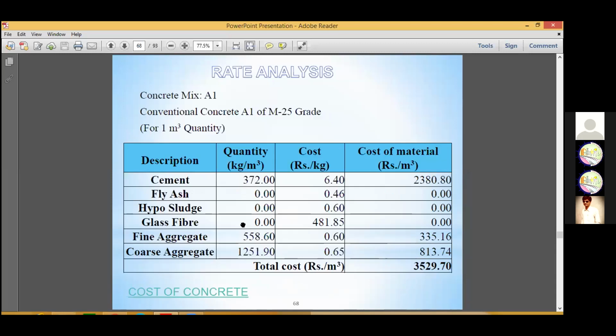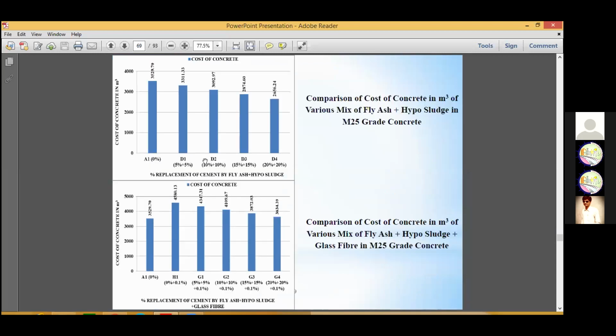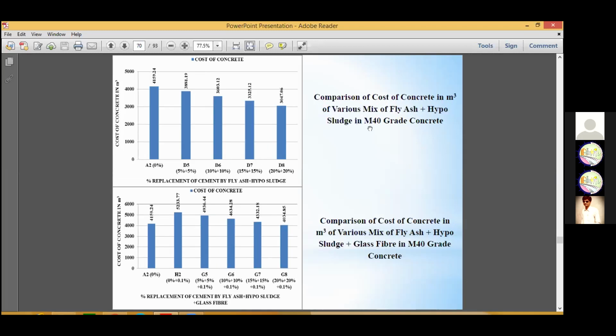In the same way, the M25 grade of concrete, we have referred with around 3,530 rupees. And in the same way you have referred with the D1, D2, D3, D4 hybrid mix cost, and G1, G2, G3, G4. So D2 is 3,090 and G2 is 4,100 for the M25 grade of concrete. In the same way for M40 grade, D5 is 3,800 and G5 is 4,900. Compared to A2, the cost is somewhat increased due to the glass fiber cost. But if you go with your own glass fiber production, then definitely the cost is decreased, and we get lots of benefits from this sustainable concrete.